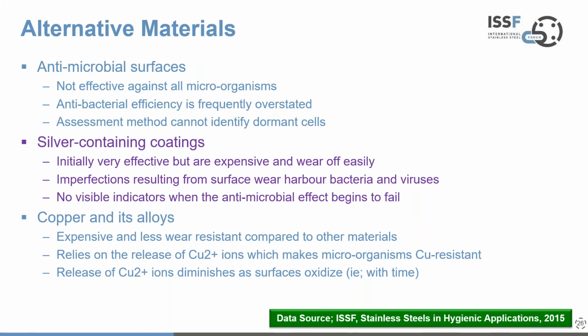And then last, we come to copper and its alloys in this sort of trilogy of alternative materials. Copper is expensive. It is not a cheap material. It's less wear resistant when compared to other materials. However, it does rely on the release of copper 2+ ions, which at the start is fantastic and copper is really effective. But also the release of these ions makes microorganisms copper resistant. So in other words, the release of the copper ions and their effect actually diminishes, because you get diminishment resulting from the surface oxidation effect, which is a feature of how copper and its alloys behave. But also the buildup of copper resistant microorganisms means that the copper ions that are released become less effective as well. So there's a double whammy there, which is not so helpful, even though the material is fantastic at the start.